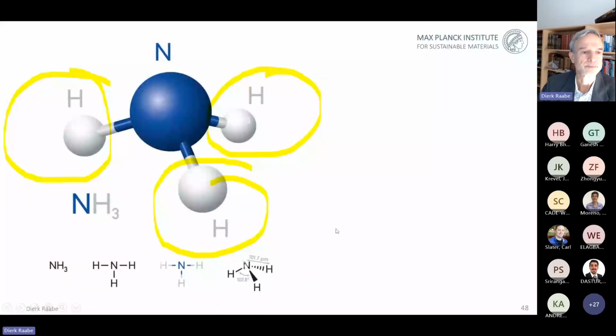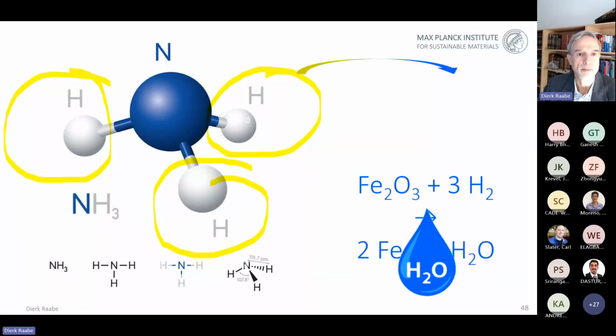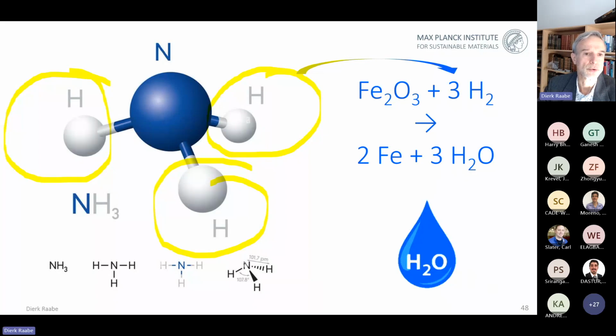Now, one little sidestep is, as I mentioned in the beginning, the use of other vectors. Here we use, for instance, ammonia to reduce iron oxides. And ammonia is here, of course, a carrier, not the complete reductant, but we extract the hydrogen in the reactor. That means we don't use a splitter, but we exploit the fact that iron, once it's formed, is a very efficient catalyst to split ammonia into nitrogen and hydrogen.